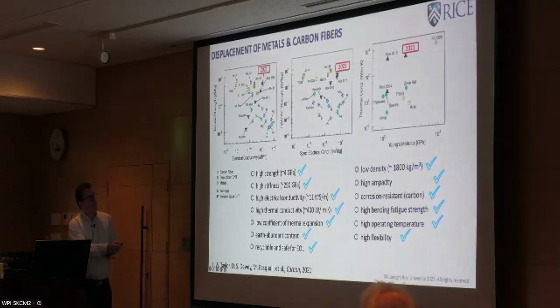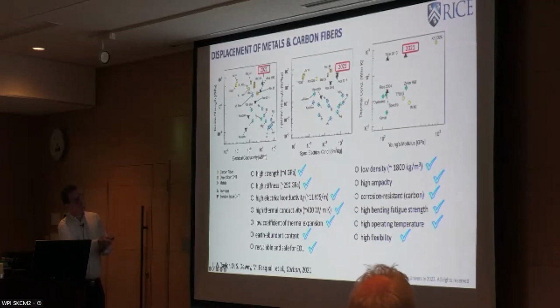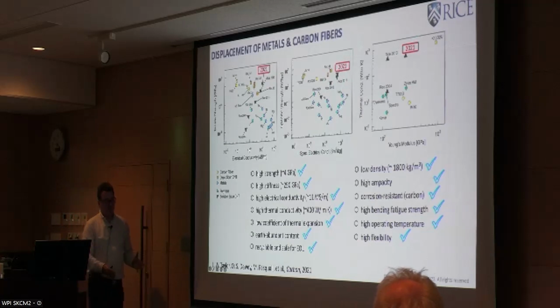So here properties went up with time, and so now what you see here is strength divided by mass, which is a better measure of how good a material is, and these are electrical conductivity divided by mass. So you see, it's not the strongest material, it's not the most conductive material, but it's in the ballpark. So if one wanted to do material substitution, and substitute metals with these materials, you could do that now on the basis of properties.